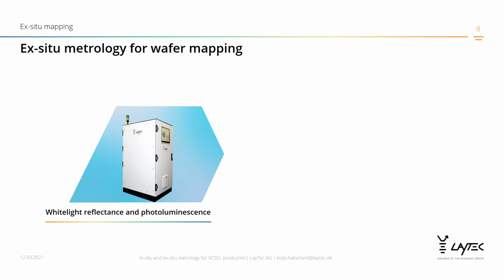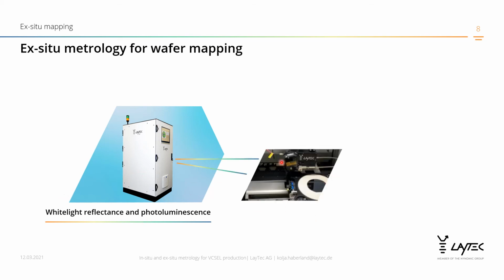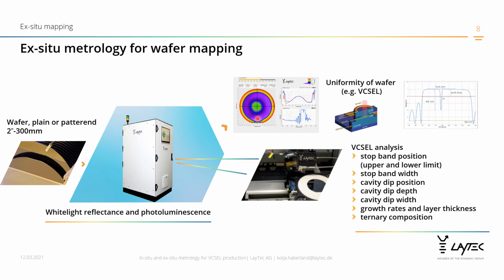After the epitaxy process, the wafers can be characterized ex-situ in a mapping station with white light reflectance and photoluminescence. Inside this box, we see the optical head and the wafer. Wafers are loaded, and the result is a two-dimensional mapping of the reflectance or photoluminescence of the epi wafer, providing, in case of VCSELs, stop band position, stop band width, cavity dip position, cavity depth, cavity dip width, growth rate and layer thickness, and ternary composition.